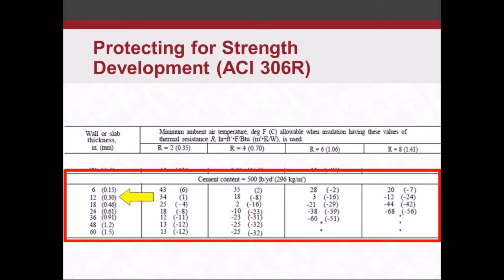What we're doing here is using the heat of hydration of the cement, and there's been a lot of research done into the heat of hydration. We're capturing that heat and not letting it out, using these different R values to make sure that we're keeping our structure at that minimum temperature. What I'm showing here with this arrow is a 12-inch wall, and we're expecting temperatures to get down to 3 degrees, which, by the way, is about as cold as that local project got when I was taking some pictures. We need an R value of 6, which isn't much. Again, this is specific to 500 pounds of cement per cubic yard, that particular wall thickness, this air temperature, and these R values. And again, we're using the heat of hydration to make sure that our concrete temperatures don't decrease.